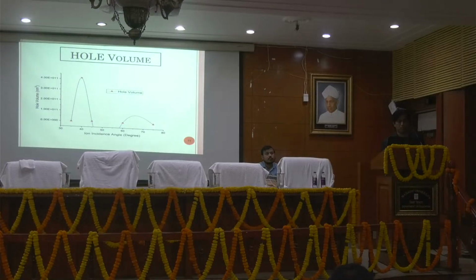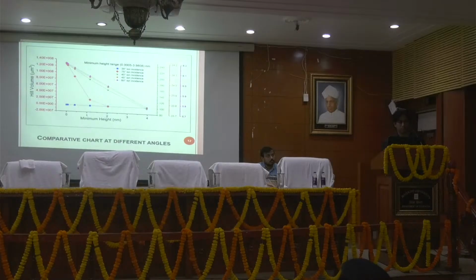These are also the other results which have been calculated for the hole volumes. Hole volume has been calculated because it is very important for the generation of 2D material by various synthesis routes. Like we want to use the chemical vapor deposition method because it is the cheapest method today. So that we can generate small layers or thin layers of a 2D material like MoS2, alpha MoS2, SnS2, SnS, or other 2D materials. These are the comparative chart of hill volumes and the maximum height for the holes.